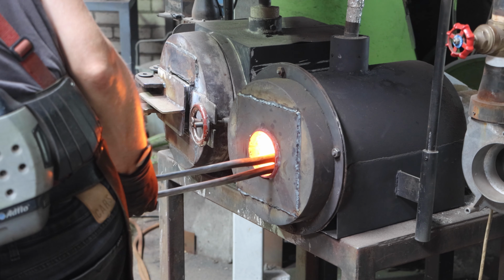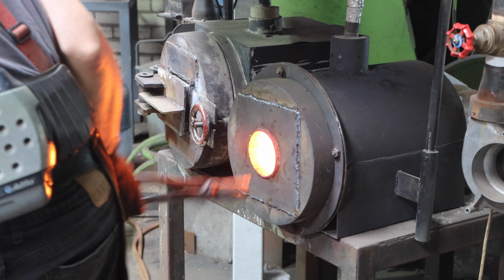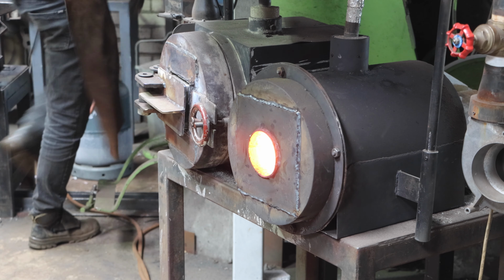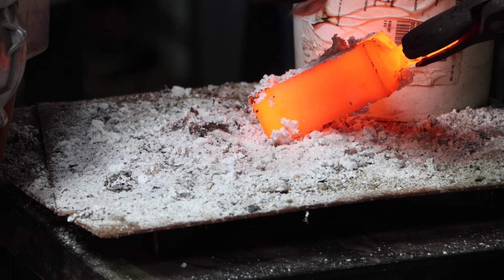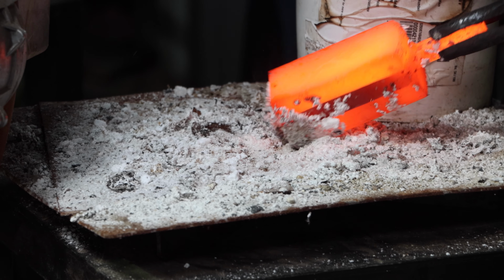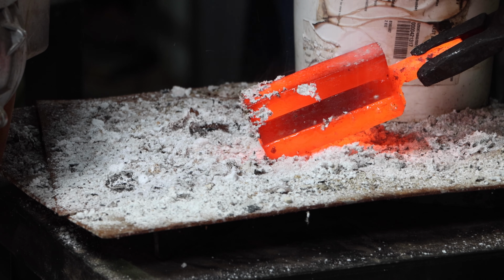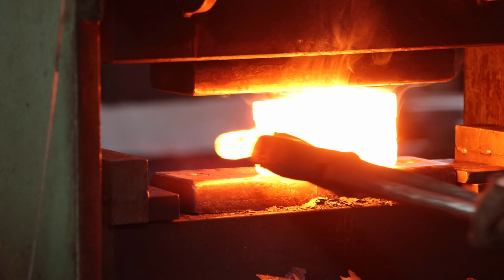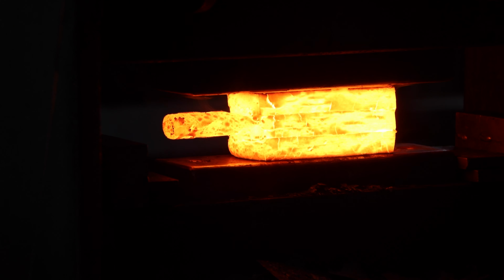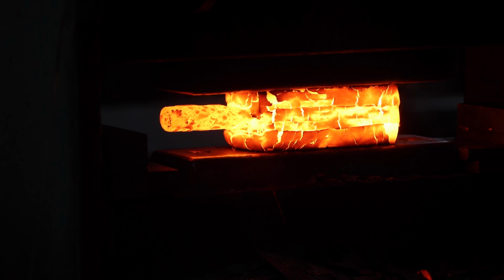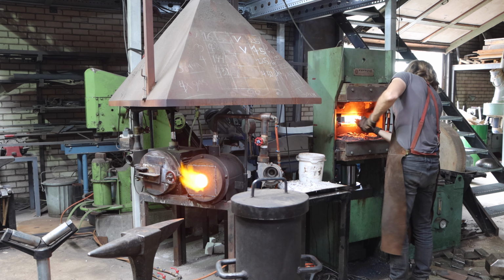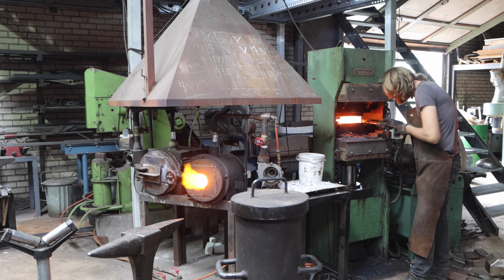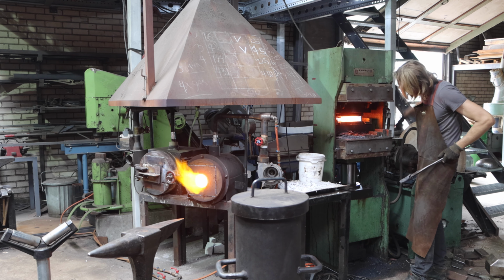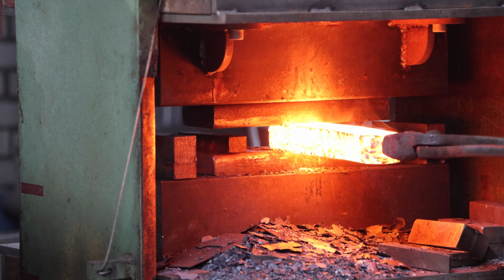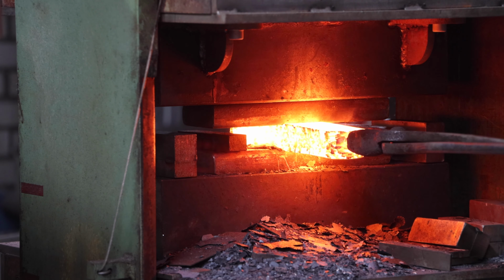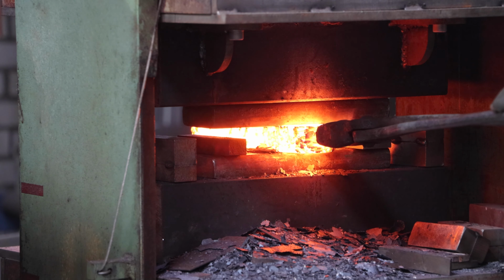The borax is very aggressive on the forge. I have to refurbish it once every 2 years. The forge is lined with an isolating blanket and shielded with refractory concrete. The forge can go up to 1500 degrees Celsius. 1200 degrees Celsius is needed to forge weld. The melting point of steel is somewhere around 1500 degrees, but this depends on the steel alloy. If the melting point is reached, it will completely ruin the billet.